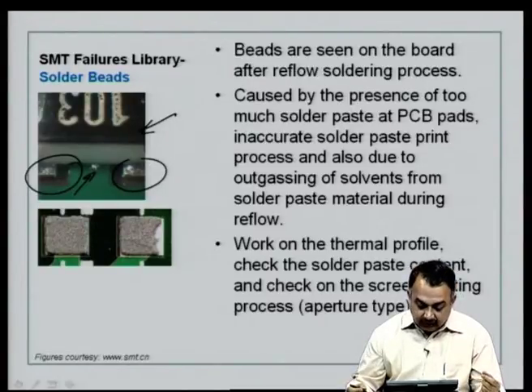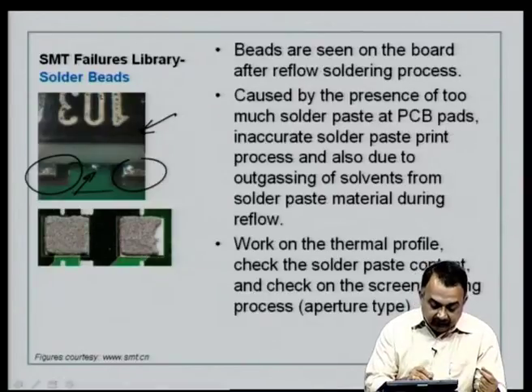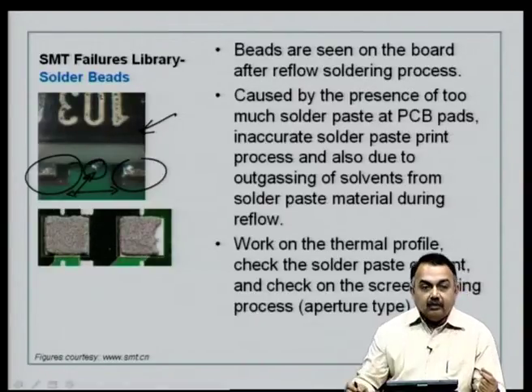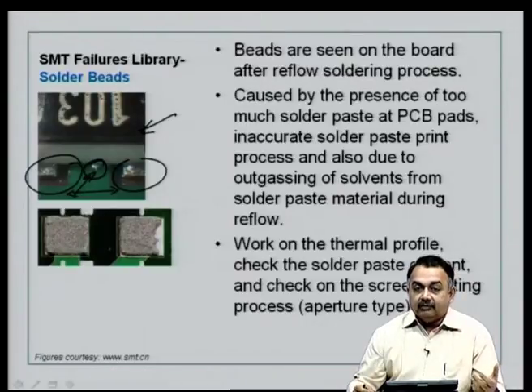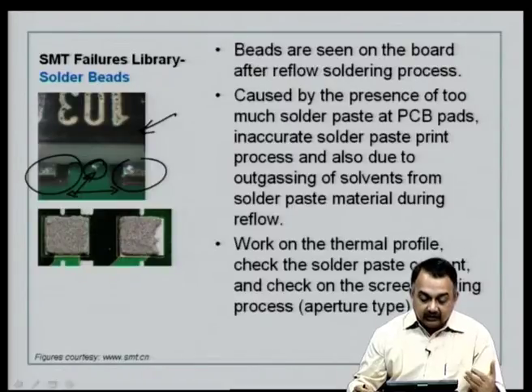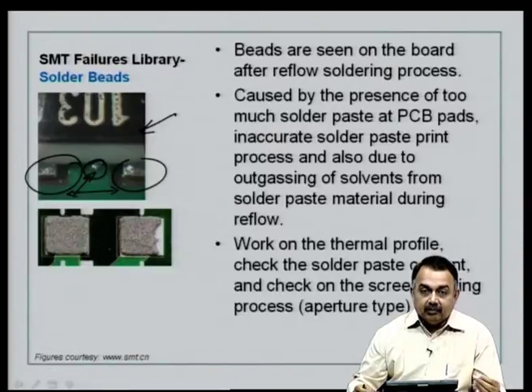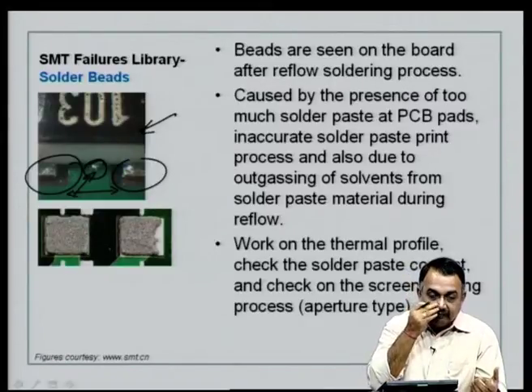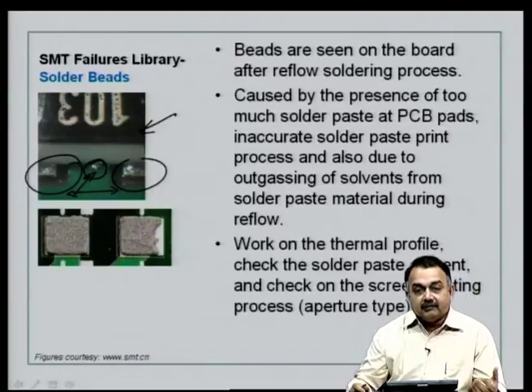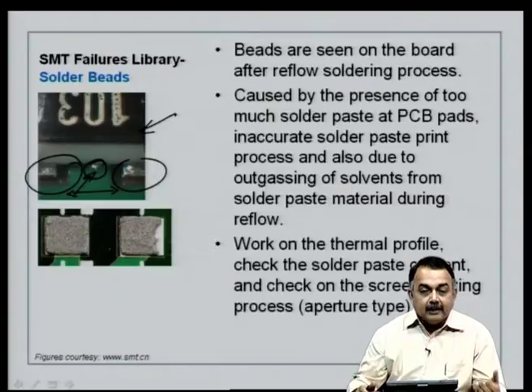Now, could this be a defect? Yes, if this pitch is very small and if there is a bead that you have noticed or not noticed and you think it is not going to harm the package or the board, then you are wrong, because this could be a very important seed point for corrosion. It could damage the package, it could result in short over time because of some kind of a whisker formation, or it could contaminate the surface of the board and form electrochemical connection bridge between adjacent pads or tracks and so on.